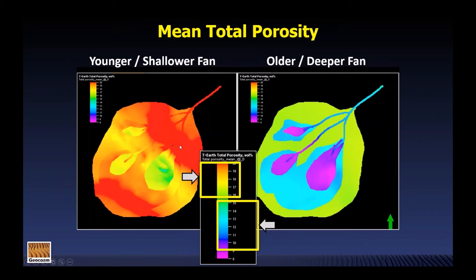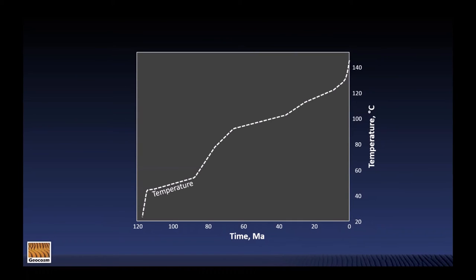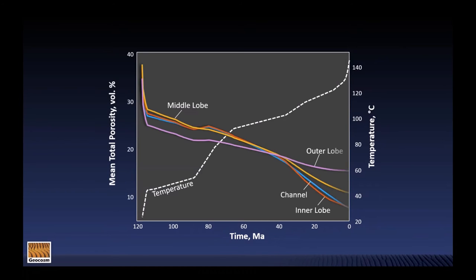So what we can glean from this is that the relative difference in reservoir quality between different facies is not necessarily constant through geologic time. It could be very dependent on the burial history. So to get a better handle on what's going on here, let's do this. We're going to take a burial history from the center of this fan, and we're going to subject all four of these facies to that exact same burial history and see how it responds through geologic time. So just to remind you, here's what that temperature history looks like, and of course there's an effective stress history to go along with this. But now let's look at the total porosity through geologic time for those four facies.